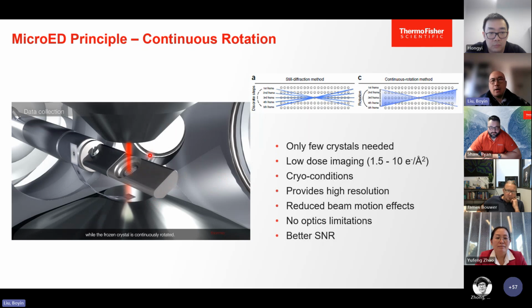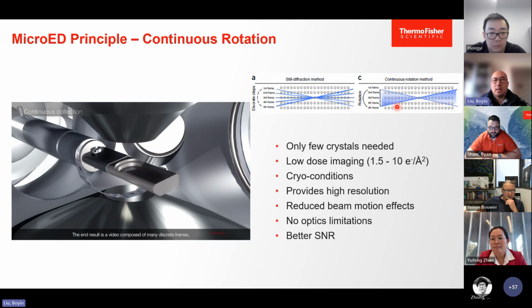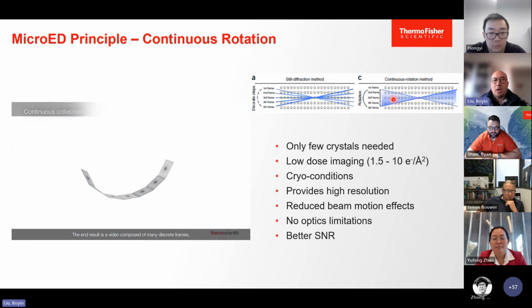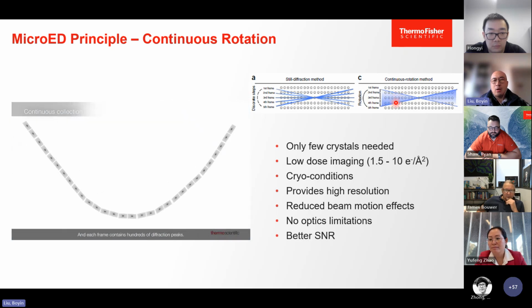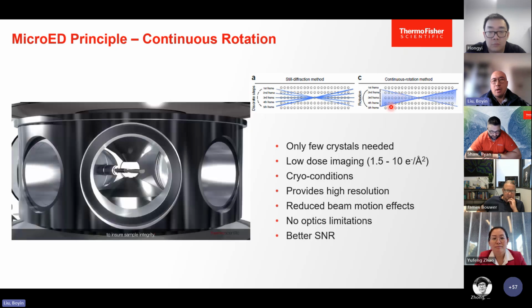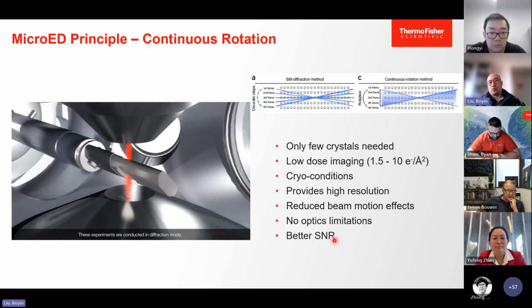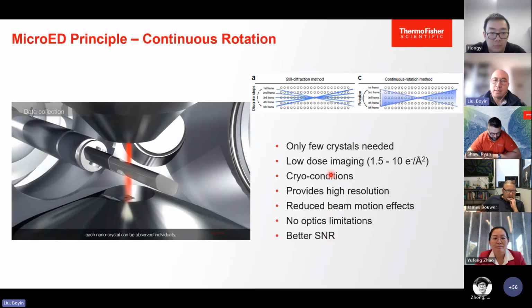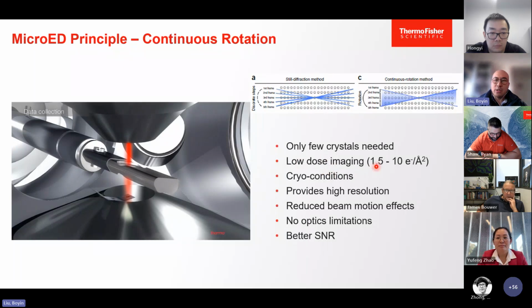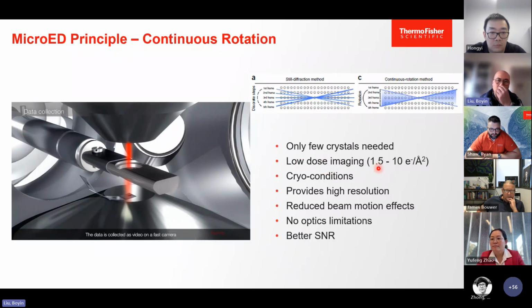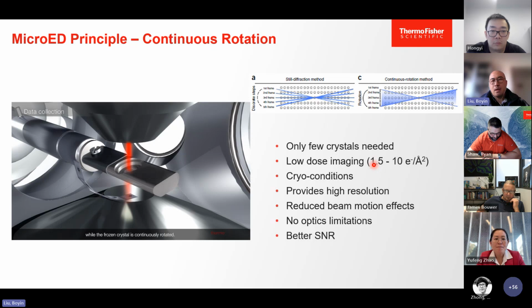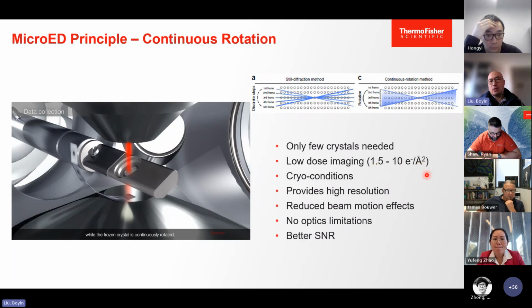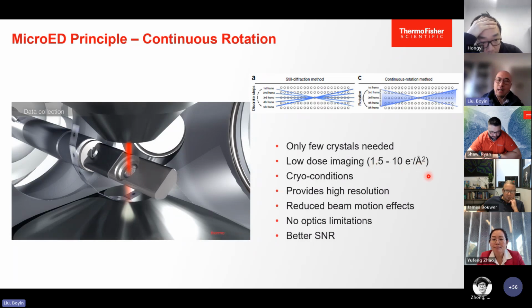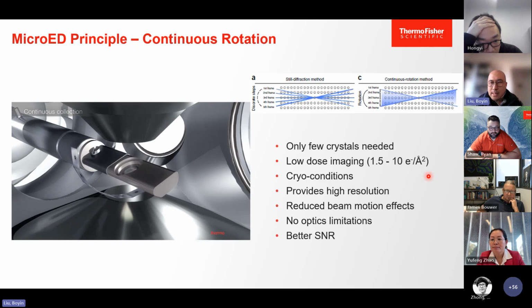In that case, for every exposure, you're actually sampling a wedge of the sample. That's why the MicroED diffraction looks sharper and gives you a better signal-to-noise ratio, because it's sampling a wedge of the sample. And it's low-dose imaging. Overall dose has to be maintained roughly between 1.5 to 10 electrons per square angstrom. Sometimes it can go up to 25 electrons. It really depends on your samples.